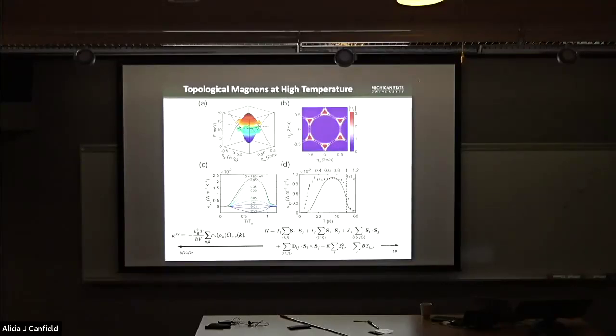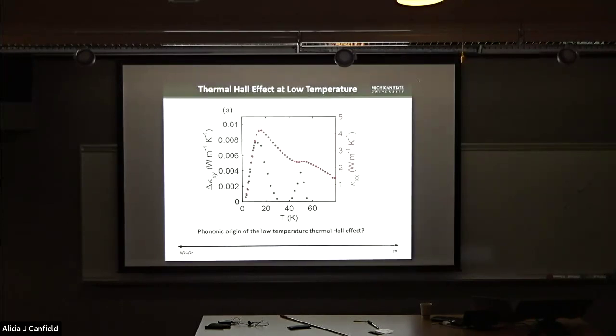So this kind of suggests that at high temperature, our thermal signal is dominated by the topological magnons, as we hoped to see. But in the meantime, we have to see that at low temperature, there's a large discrepancy between the experimental data and the calculated results. So what's the cause for such a discrepancy? As I mentioned earlier, from the longitudinal thermal conductivity measurements, we know that the system shows a very strong magnon phonon scattering, right? So naively, this might be something related to the magnon phonon scattering.